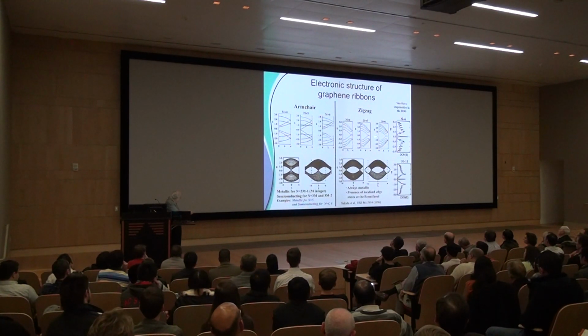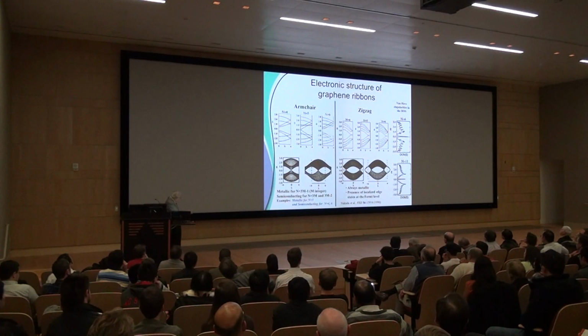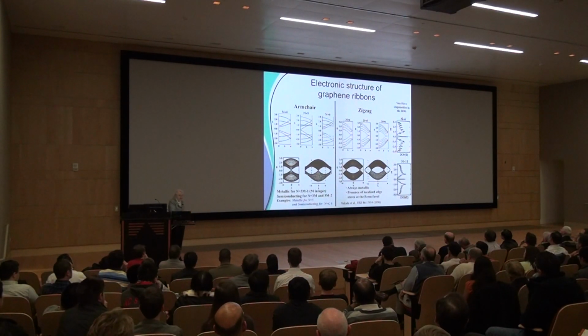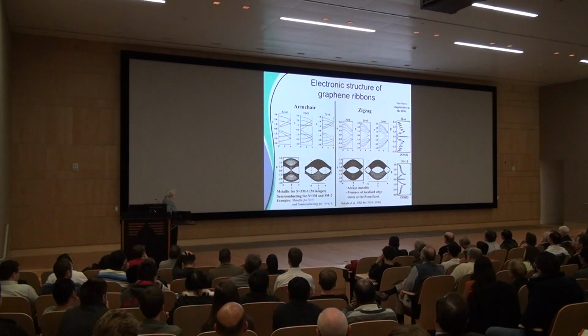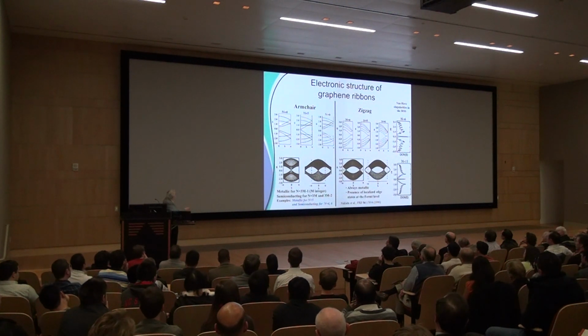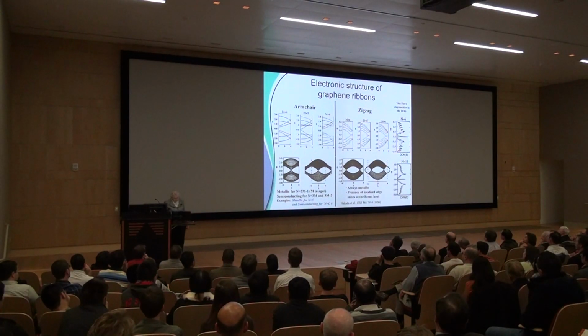And you see for a zigzag, no matter what the ribbon width, it always has a high density of states at the Fermi level, so it's always metallic. All the zigzag ribbons are metallic. But the armchair, we have a choice. We can have a metallic case, like n equals 5, but then we can have semiconductors, n equals 4 and n equals 6. So this is very much like nanotubes. We have semiconducting and metallic, with the same frequency of occurrence.